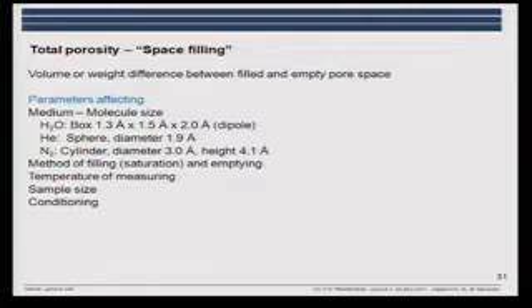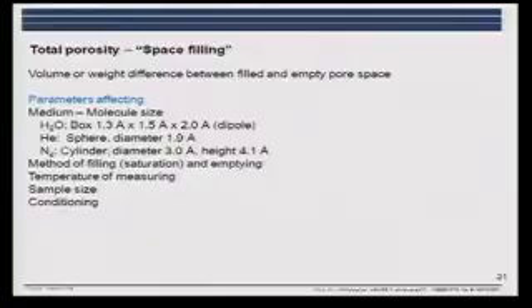Then the total porosity, the space filling. That would be the variation in volume, either because you press a volume in and you can measure the volume change, or the amount of material going into your sample, or you measure a weight change. And the material entering into the sample will depend on the size of the molecules. If you use water or helium or nitrogen, they have different sizes, and they also are hydrophilic or hydrophobic, so they have a different interaction with the material. Then the method you use to fill the sample, the method of saturation, I'll come back to in the next slide, and the method you use for emptying the sample will have an impact.